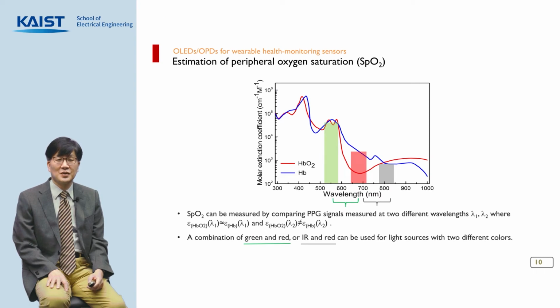SpO2 can be measured by comparing PPG signals measured at two different wavelengths, let's say lambda 1 and lambda 2, where absorption coefficients are the same and different, respectively, for hemoglobin with oxygen and without oxygen. A combination of green and red, or IR and red, can be used for light sources with such two different colors.